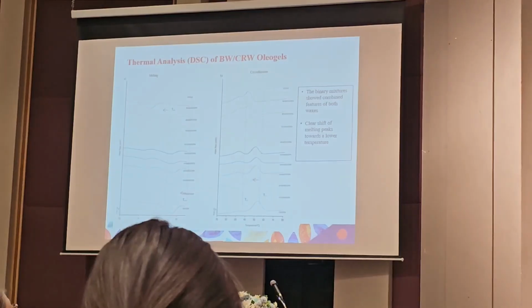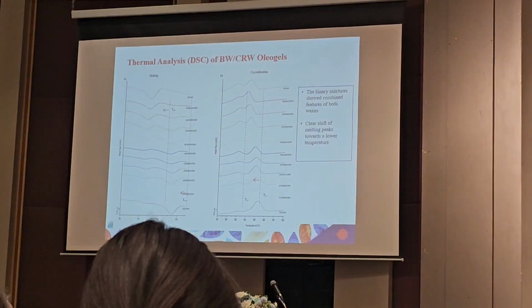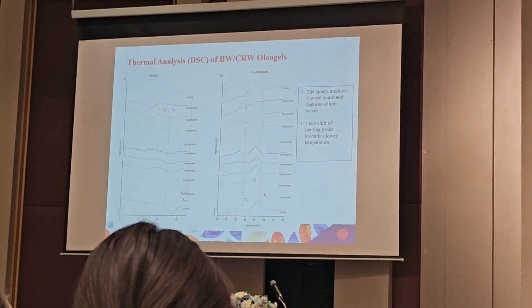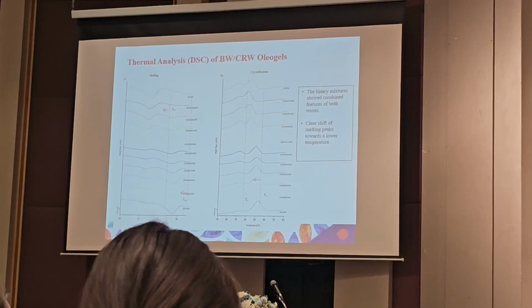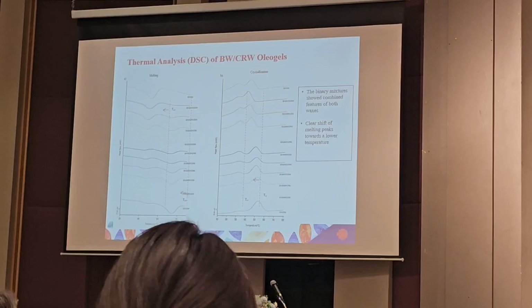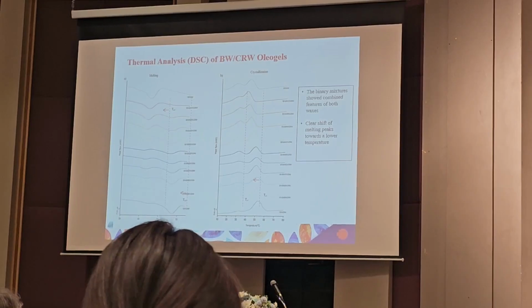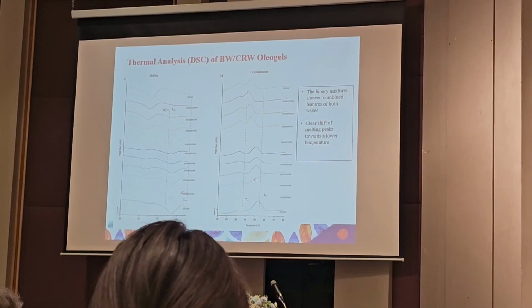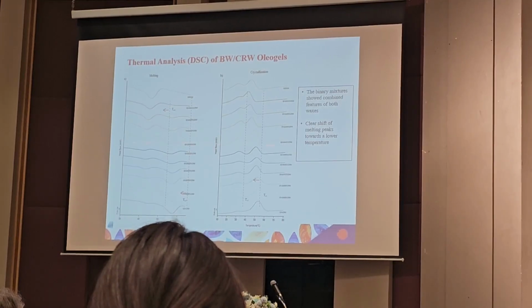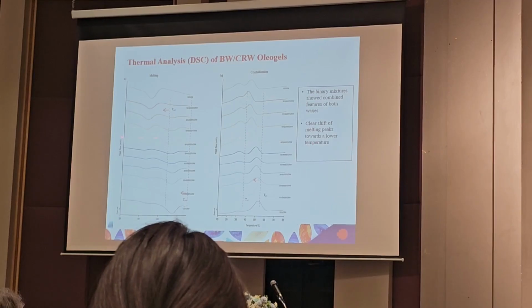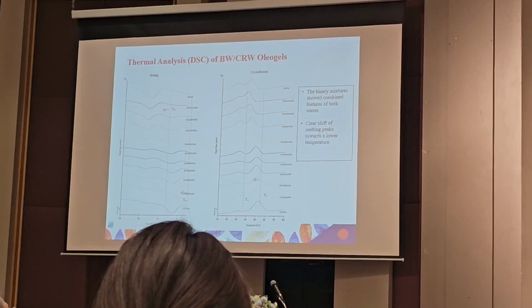When it's consumed, possibly depending on the concentration of each of the gelators, we may get different greasiness perception in the sensory. That needs to be, of course, tested. So left is about melting and right is about crystallization. And when the concentration is 50%, again, yes, we get two peaks. That's showing that these two haven't actually mixed at the molecular level.